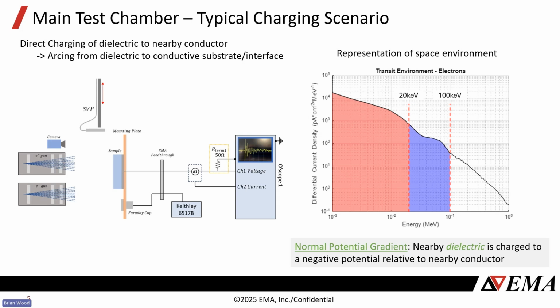Essentially, if you're trying to do an in situ type of exposure, where you're trying to accurately represent what the sample is going to be receiving in that moment, this is the method we use: we plot the differential flux, separate the energy bins, integrate to get the flux to irradiate with, and choose which energies to irradiate with. Some of the typical things we've done is going to 100 keV max for a 100 keV gun. For this instance, we picked 20 keV to represent the other bin. That's a normal scenario for us if we're doing this type of charging.